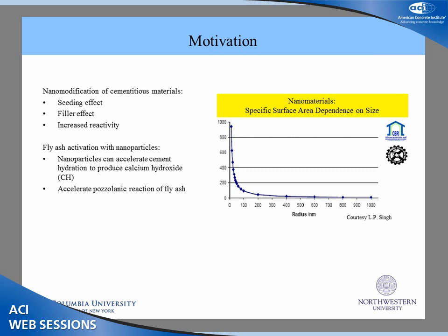So the motivation behind implementing nanomodification is there's been a lot of work being done on the use of nanoparticles in cement-based materials, and they've been showing potential to significantly enhance the properties of our material. And this is very intimately tied to its fine particle size. So we look here, this is the relationship between particle size and then the specific surface area that these particles introduce. And nanoparticles are considered to be below 100 nanometers. And you see that once you go sub 100 nanometers, the specific surface area dramatically increases.